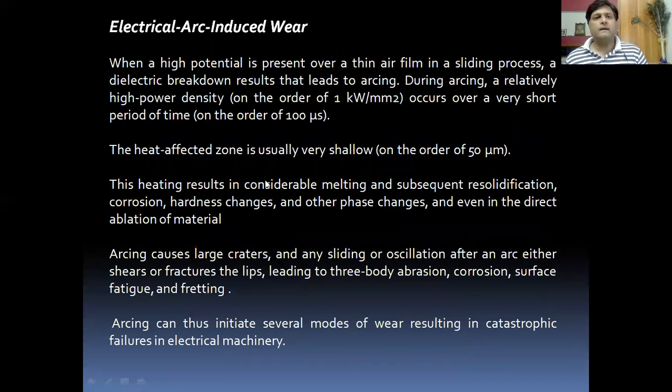Now, as far as electric arc induced wear is concerned, this happens between two sliding surfaces when the air film is thin and a dielectric breakdown takes place between the two surfaces, which leads to arcing between them. This arcing takes place due to a relatively high power density, of the order of 1 kilowatt per mm square, built up between the two surfaces for a very short period of time, around 100 microseconds. So this will create a dielectric breakdown and arcing between the two surfaces.